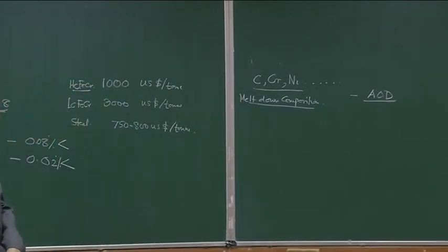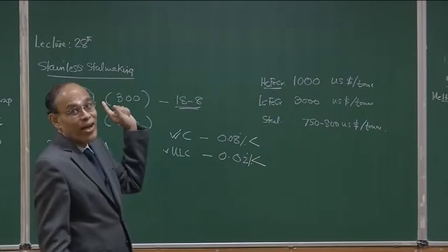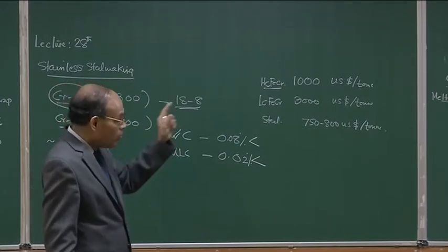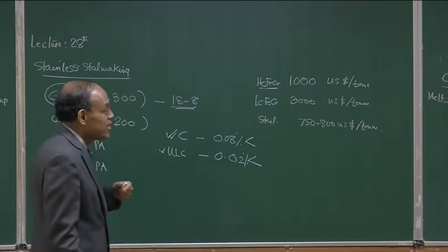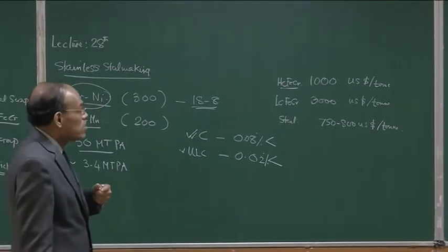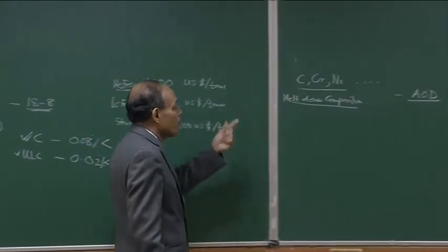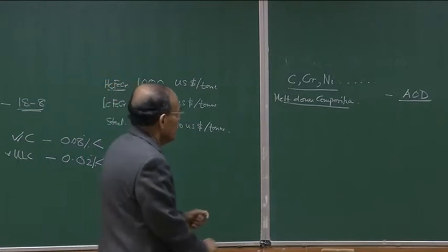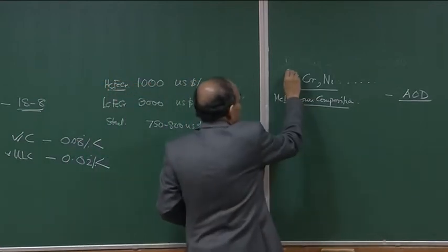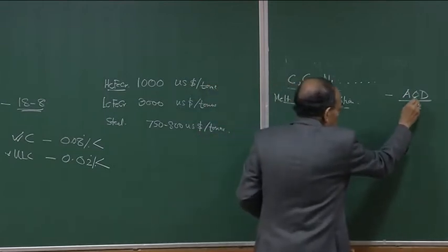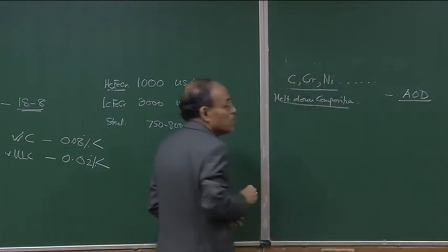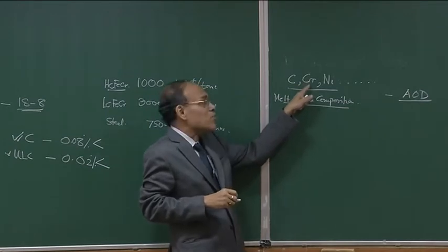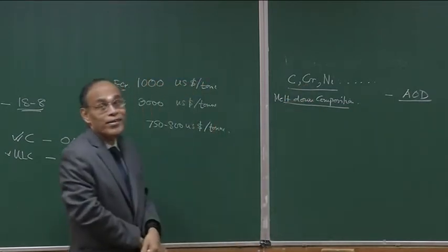So, it is under argon and oxygen that decarbonization is going to take place, and as I have indicated, at meltdown the carbon concentration is high because of the use of high carbon ferrochrome. We are using high carbon ferrochrome for economic reasons, I hope that point is clear to you. Therefore, we have to drive out carbon, and for that you put in oxygen, which will react with carbon, but note that chromium is also a partially oxidizable element. So, chromium can also react with oxygen.